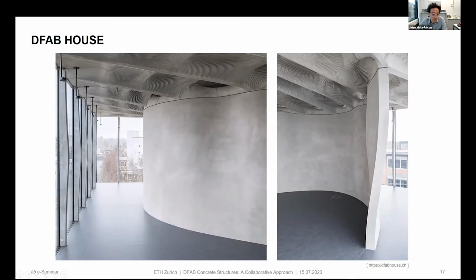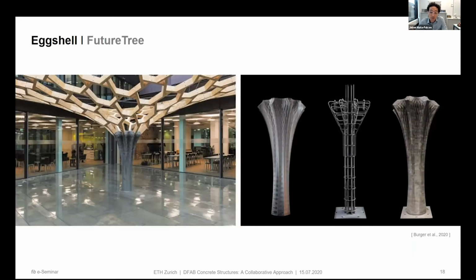On the left are these smart dynamic casting facade mullions, and on the right you see this double curve mesh mold wall. And in this case, we did not do prototype testing. Of course, we need to have a structural test to check that everything behaves as expected, or that we can explain it. Then I think Eggshell technology or other technologies derive from mesh mold, in the sense that we have a set on demand process that can be used to have this slipping minimum formwork, but also can be used to reduce the formwork pressure. And this allows us to have minimum formworks.